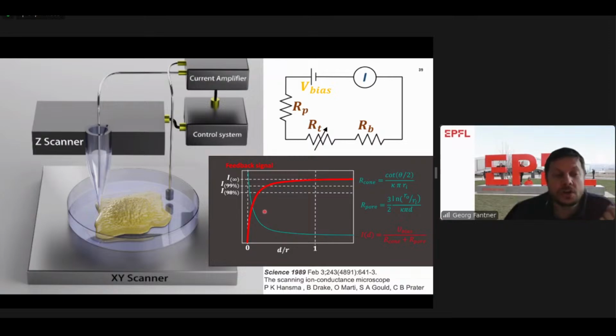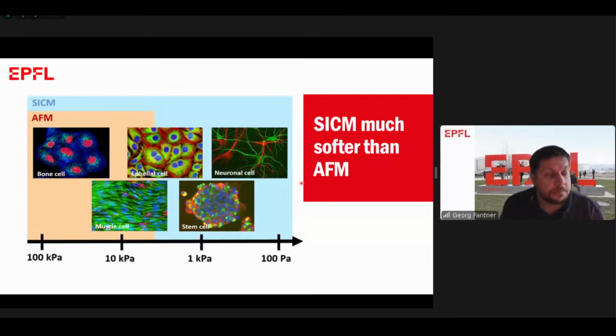So now we have a non-contact proximity sensor. We can tell where the surface is by looking at this ion curve without ever having touched the surface. And if we do this now at every point in the image, then we have a non-contact way to image the topography of the cells. And this is great because now we can address not just the stiff kind of cells like bone cells or muscle cells that we can do with AFM, but really more the interesting, very, very soft cells, stem cells, neurons that are just simply not addressable by AFM because they just get completely broken.